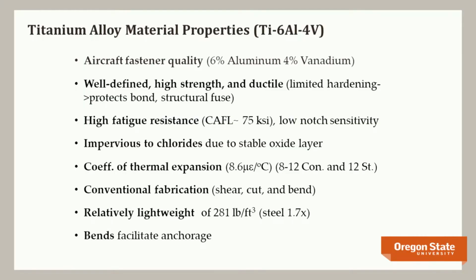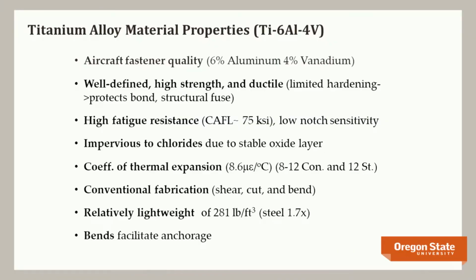It has high fatigue resistance with a constant amplitude fatigue limit of about 75 KSI. It has low notch sensitivity, right? So we're not worried about fatigue of the titanium, we're more worried about fatigue of your reinforcing steel. Impervious to chlorides because it forms a very stable oxide layer almost immediately, and that's why we use it in joints. We're very salty creatures, and we don't worry about corrosion of your hip or your knee.